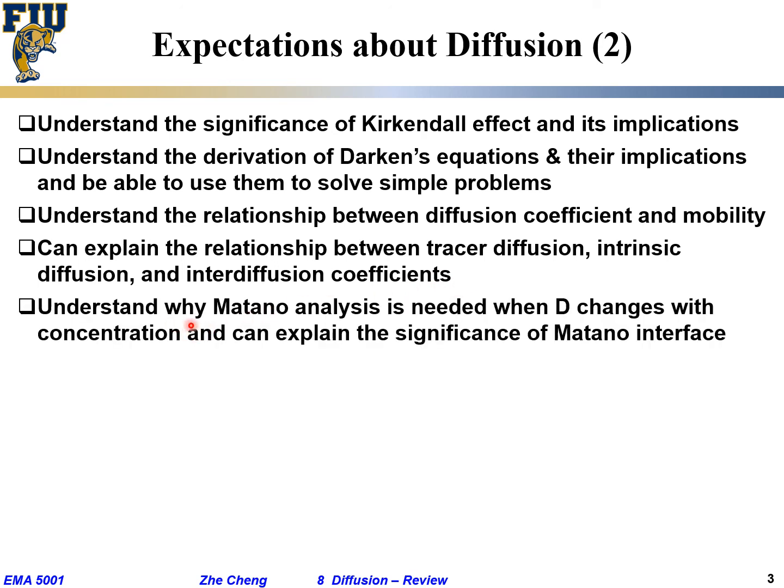And I also expect you to be able to understand some Matano analysis. And why this analysis is needed, because we said the diffusion coefficient actually may change with concentration, and for those situations quite often there's no analytical solution, which means even if we have the concentration profile, we cannot easily fit the data to get the diffusion coefficient, and then we have to do this analysis in order to solve graphically the diffusion coefficient at different concentration.